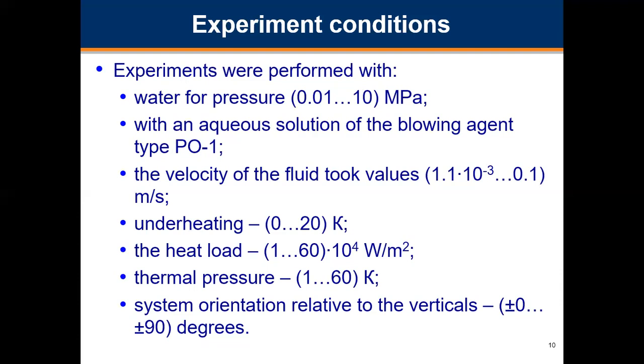Experiments were performed with water for pressure from 0.01 to 10 megapascals, as well as with a solution of the surfactant type PO1. The velocity of the fluid took values 1.1 times 10 to the power of negative 3 and 0.1 meters per second. Under heating, from 0 to 20 kelvins. The excess fluid was 1 to 14 of the steam consumption. The heat load was 1 to 60 times 10 to the power of 4 watts per square meter. Thermal pressure was 1 to 60 kelvins. System orientation relative to the vertical from 0 to 90 degrees.